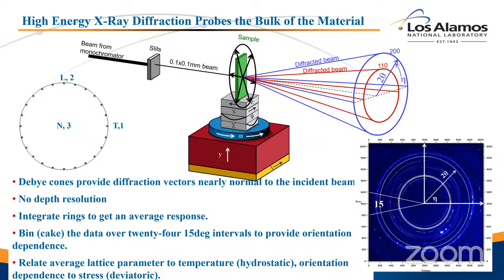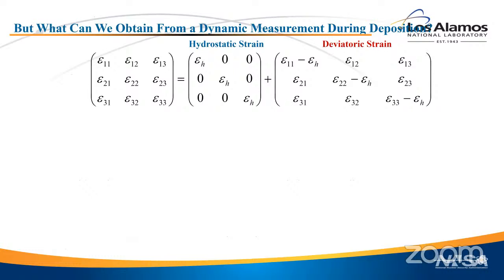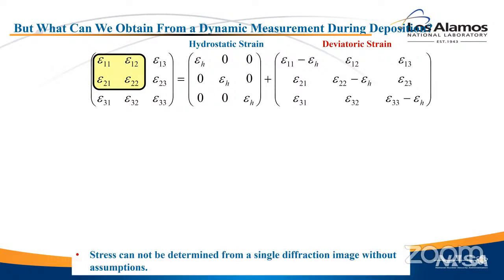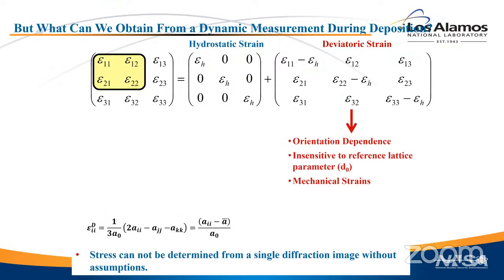And we do similar things to separate phase fractions, how the phase fraction affects intensity from how texture affects intensity. I'm not going to go into details of that. So if you think about the strain and how that lattice parameter measurement happens, if you take the strain tensor, which is on the top left, there are 6 independent components. You can separate that into a hydrostatic part and a deviatoric part. If you calculate a strain from the deviatoric part, where you basically subtract out the average lattice parameter, you see that the deviatoric part becomes relatively insensitive to the reference lattice parameter. And that's where one of our problems always is: how do you measure a reference lattice parameter? Because it's just hard to get.